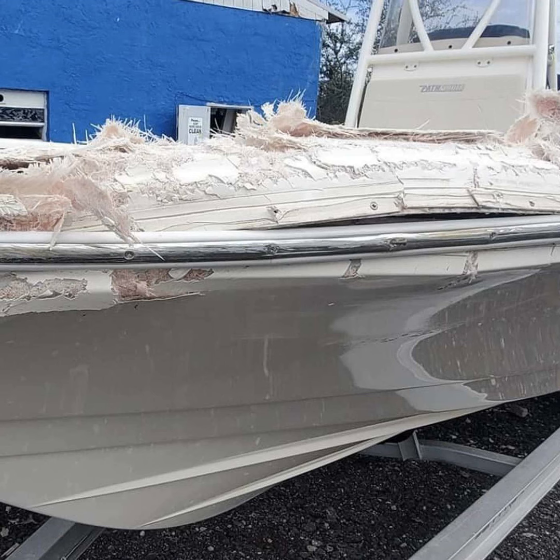And this goes twofold for stringer damage. If you're seeing the stress cracks inside the strake from stringer damage inside the boat, you could put 3 inches of fiberglass on the outside of that, and it's not going to help you. You've got to get in there and look at the stringer, retab the stringer, figure out what failed, and address that structural issue as well as the failed laminate in the hull. So you're looking at 2 different repairs, kind of, in a situation like that. That's a little more complex than what we're going to get into today. So we're just talking about a general repair.